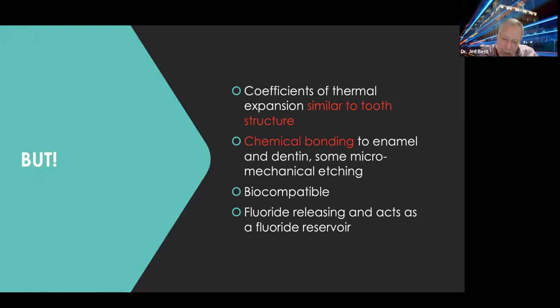And that is because that area has remineralized from the fluoride release of the glass ionomer in towards the DEJ. And what's also really important is that it doesn't make a difference how you supply the fluoride to the patient. So if a parent, for sake of argument, is against water fluoridation, but they'll use a fluoridated toothpaste, that's enough of a source to supply fluoride for the glass ionomer. If they don't want fluoridated toothpaste, but they'll use a fluoride mouthwash, same thing holds. That's enough to get embellished into the glass ionomer and subsequently released.